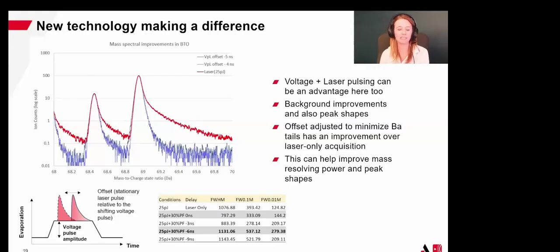And the secondary advantage of simultaneous voltage pulsing is to change and modify your mass spectral peak shapes. So the way this works is we can have a voltage pulse which is variable and can be moved slightly relative to the fixed laser pulse. And one of the things that this allows the user to do is slightly offset them. So you could offset your voltage and laser pulse so that one is slightly earlier or later in time, and change your pulse shape that's actually interacting with the specimen. Now, you may want to do this because each material has different ways of interacting with the laser pulse and the voltage pulse. The thermal and electrical conductivities can be different per material type. And as we've seen here with Dr. Jakob's work, maybe there's additional field evaporation behavior going on with the photoionization mechanisms. So that being said, one of the things that we can do is offset these slightly to change our peak shape, which has the major advantage of reducing peak tails.